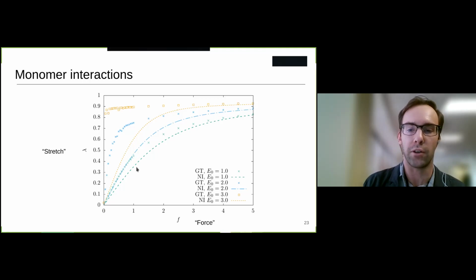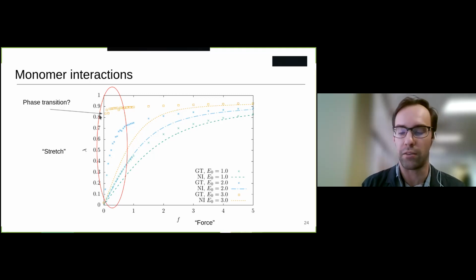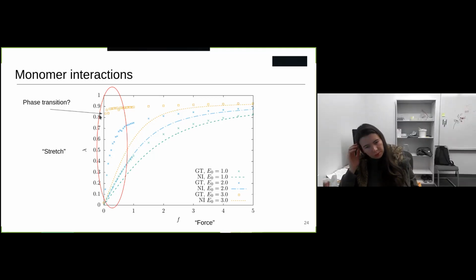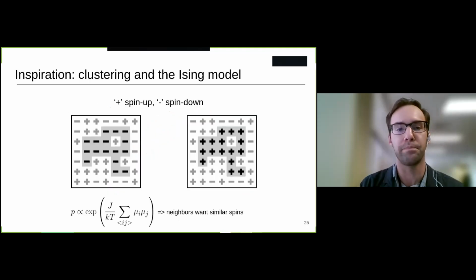And so this is a very simple, preliminary result, where I have the force on the end of the chain on the x-axis and the stretch on the y-axis, and I'm looking at this force-stretch curve as a function of different applied electric fields. The punchline here is that once you have reached a certain threshold for your electric field, the stiffness of the chain almost vanishes. And so this looks like perhaps the onset of a phase transition. But this in particular is still work in progress.